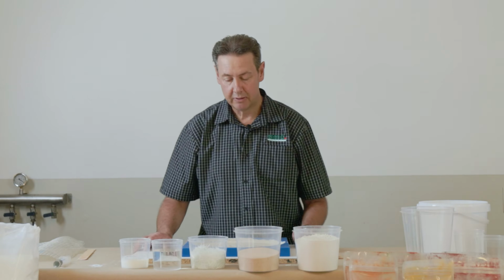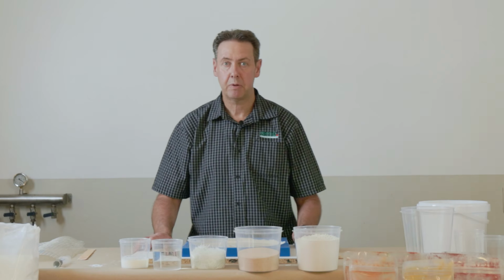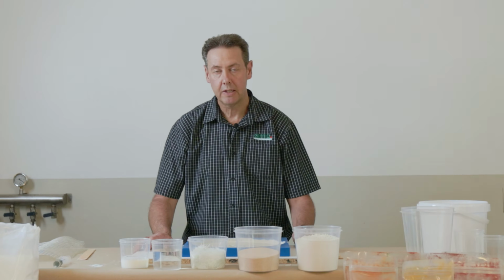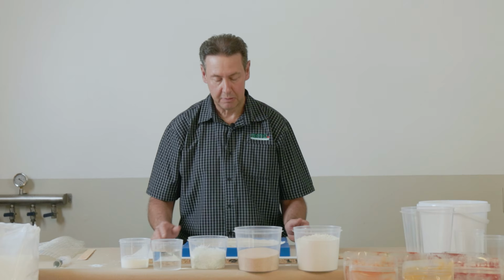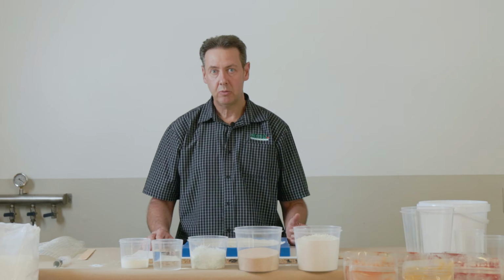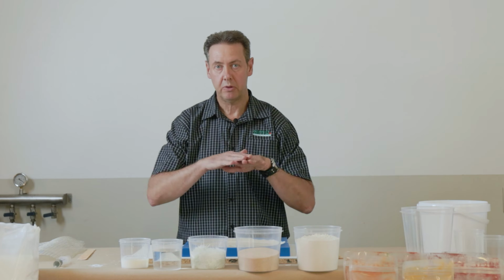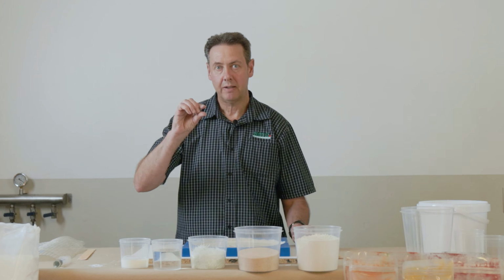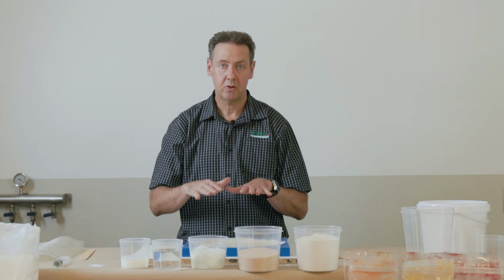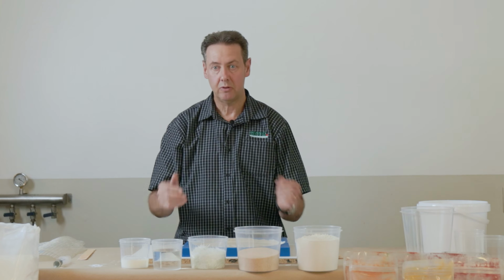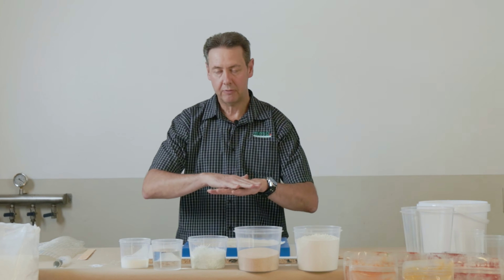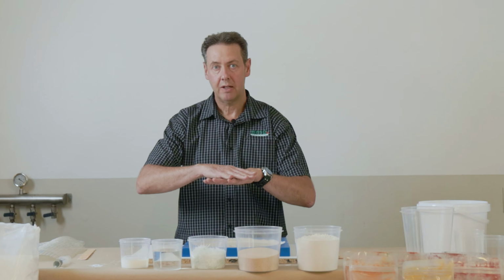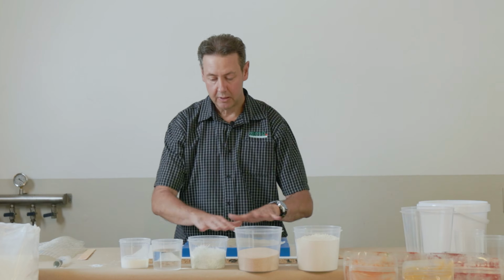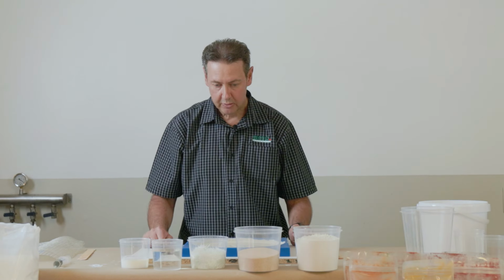So the typical laminate thickness that you can do with this GFRC is probably 20 to 25 mils. You can go thinner than that. This piece is going to be about 10 mils. And what you want to do is each layer of this reinforcing you put down, you don't want to exceed about 9 to 10 mils per layer. You can go up to 20 mils, but just do it in 2 stages. And that's to try and keep those fiber orientations quite flat. And that's what's going to give you optimal strength in this mix. So yeah, ready to go.